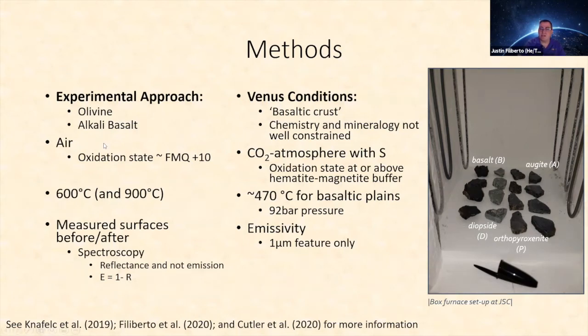These experiments were done in air, which is FMQ plus 10 approximately. The Venus conditions are at CO2 with sulfur, and the oxidation state is thought to be at or above the hematite-magnetite buffer. So we're talking about our experiments being 5 orders of magnitude more oxidizing and without CO2 and sulfur. There's a reason why this is okay, and we'll come back to that at the end.